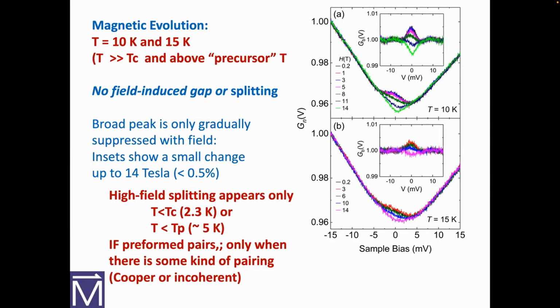Now let's go to a higher temperature. Here we are at 10 and 15 degrees, above Tc, and we're applying magnetic fields up to about 14 Tesla, and we don't see much happening. So this interesting splitting or gap that's increasing with applied magnetic field only happens when you're below Tc or below about twice Tc. When you go to about 3 times Tc, you don't see it anymore. So you've got to be close to Tc.